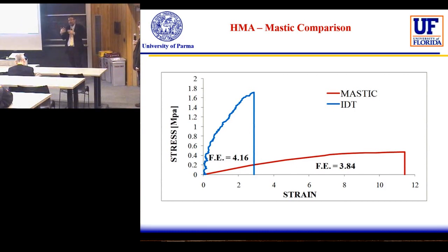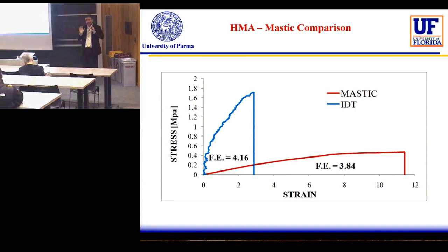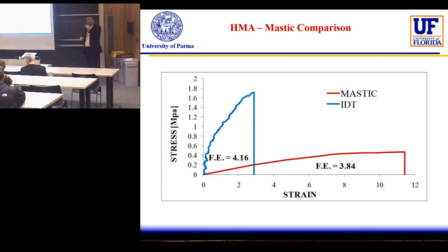This kind of material, due to the nature of the bitumen, you can heal. This is the difference. Because if you cannot heal, we are on the same page. But if you have a crack that can be healed, it's something that can go back, some kind of reversible, if it's possible to use the concept of reversible, because it's not reversible. It's a material that has a small level of damage, and the fluid nature of bitumen can come back and seal. It's not the crack that disappears, it's the crack that is closed. So if we go up, we reach a level of damage that doesn't allow the nature of the bitumen to heal. This is the difference between microcrack and...